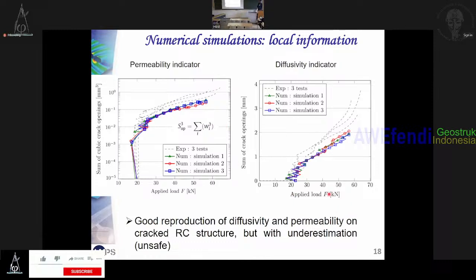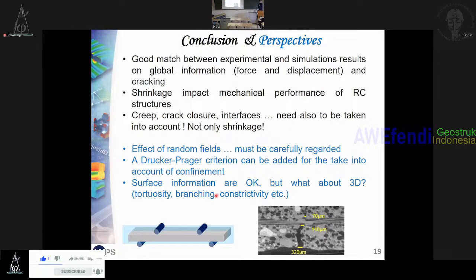So we estimate that it's possible not only to predict force versus displacement, which is quite easy with a lot of models, but we are also able to predict the crack opening. Now the conclusion. I've shown you that with this type of model it was possible to predict some durability parameters: the sum of crack opening related to diffusivity and the sum of crack opening to the power 3 for the permeability, and also to reproduce the evolution of force with respect to displacement.